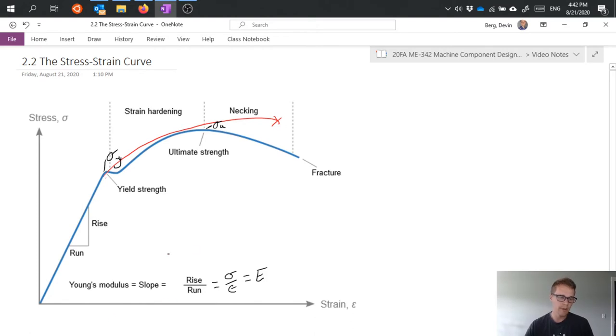One thing that we might use and one kind of standard for finding the yield in that situation is what's called the 0.2% offset. Basically what that means is if we come down here to this bottom corner, we find where the strain is 0.2%. If we take this and we go up from there and find where that crosses, then we might say that's the yield stress based on this 0.2% offset method, where the slope of this offset line has the same slope as our linear elastic region, just offset by that 0.2% of strain.